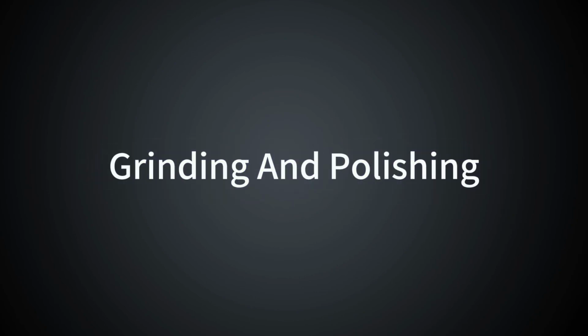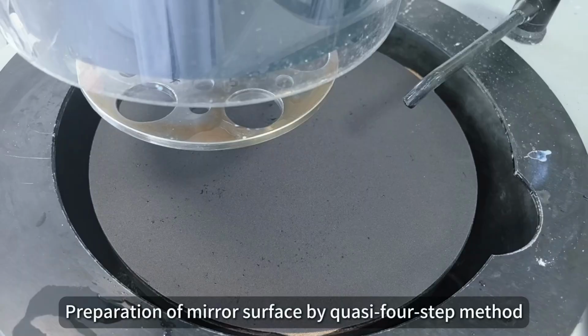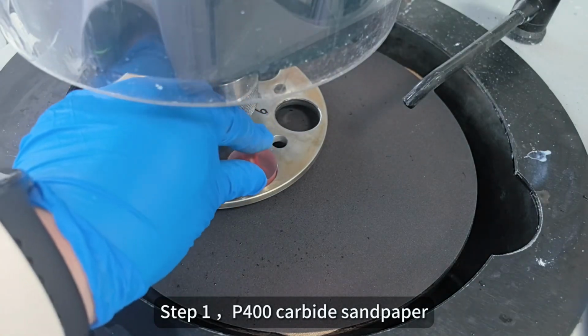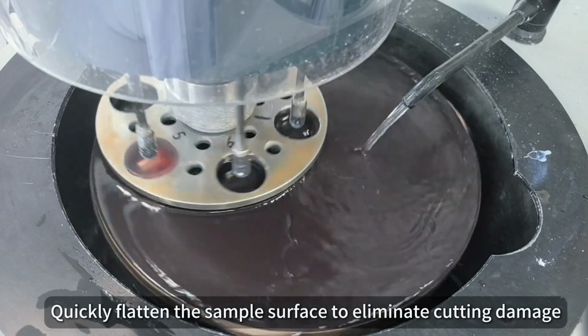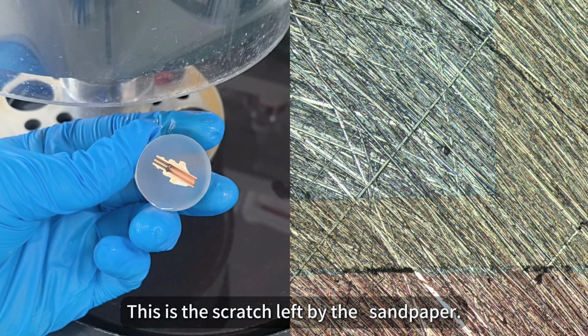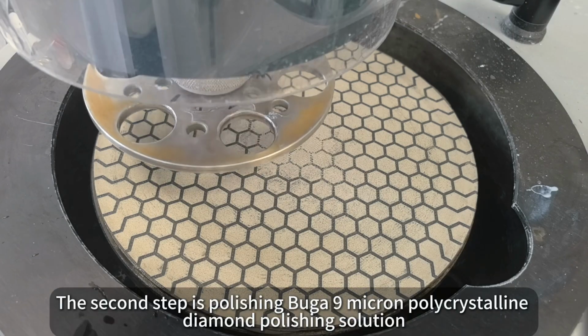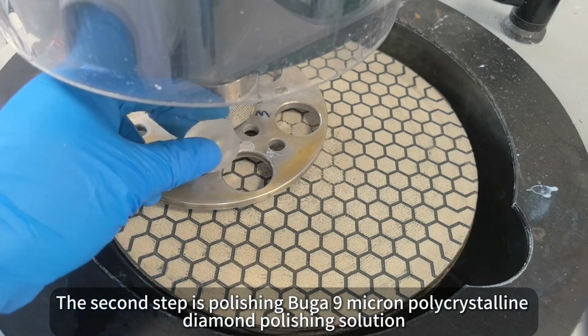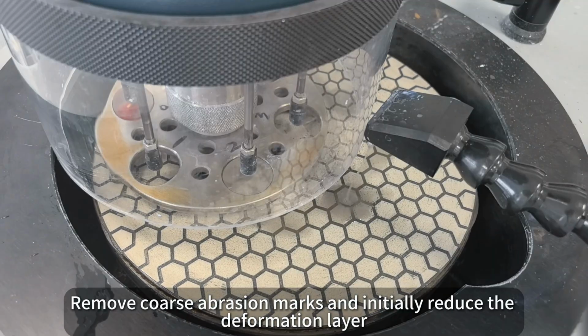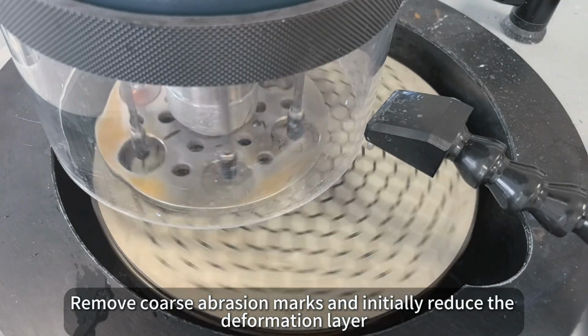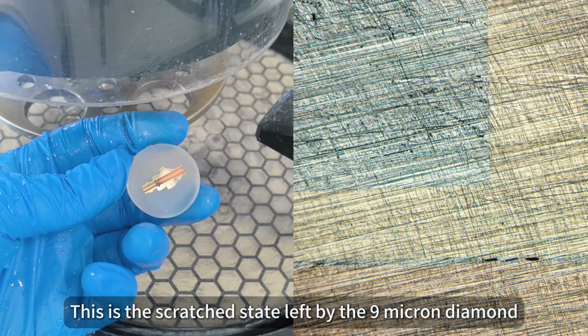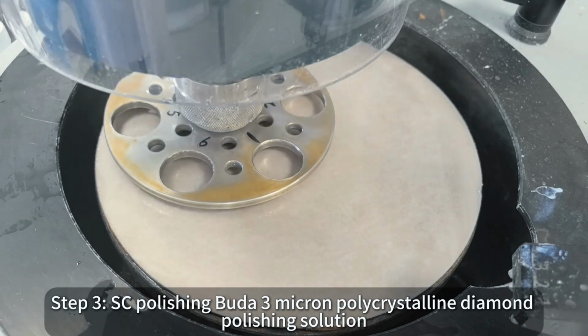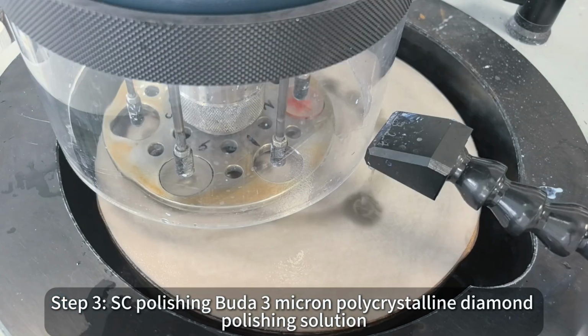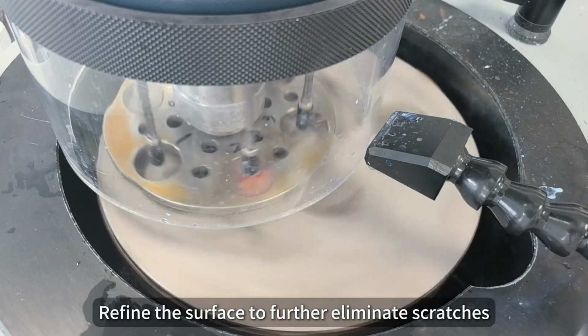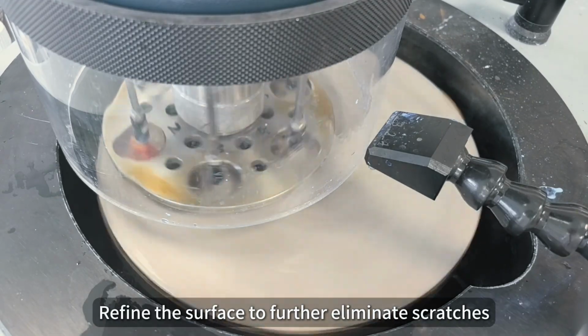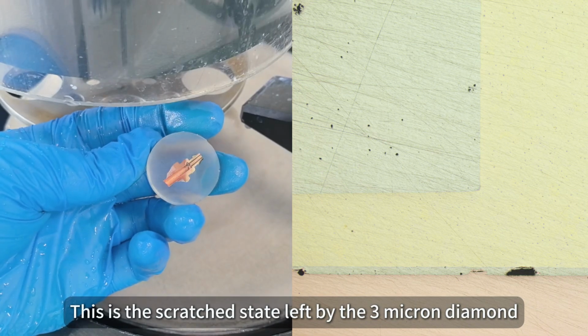Grinding and polishing. Mirror surface preparation by a quasi 4-step method. Step 1. P400 silicon carbide sandpaper. Quickly flatten the sample surface to eliminate cutting damage. This is the scratch left by the P400 sandpaper. The second step is polishing with Buehler 9-micron polycrystalline diamond polishing solution. Remove coarse abrasion marks and initially reduce the deformation layer. This is the scratched state left by the 9-micron diamond. Step 3. SC polishing with Buehler 3-micron polycrystalline diamond polishing solution. Refine the surface to further eliminate scratches. This is the scratched state left by the 3-micron diamond.